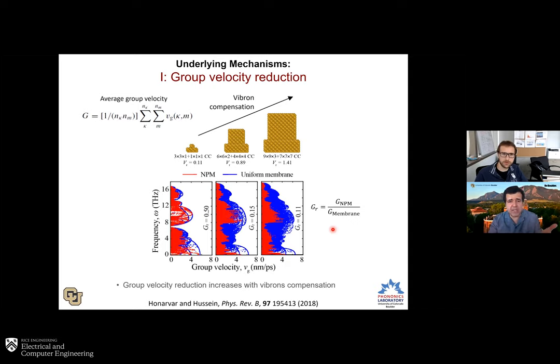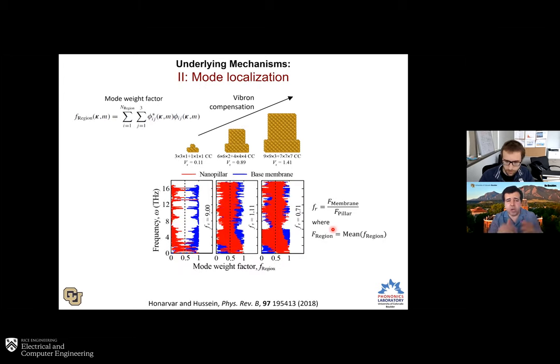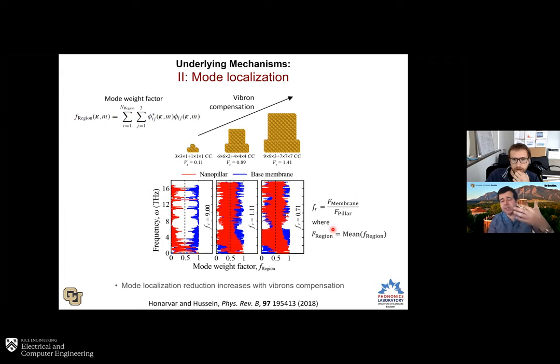Now, remember, there was also the second mechanism, which is the mode localization. So similarly, using dot products between the modes and so on, we can quantify what we call a mode weight factor, a metric that describes the extent of mode localization. And it's shown there on the right. What it tells us is that if this metric gets lower, then it implies stronger and stronger localization of motion in the modes, in the pillars, I'm sorry. And this is in fact the second mechanism that we depend on. So we want this localization to be as strong as possible. And indeed we find with this vibron compensation that the localization improves. So these two observations that came about through this approach of increasing the pillar size at a higher rate have now paved the way to really reach high performance.